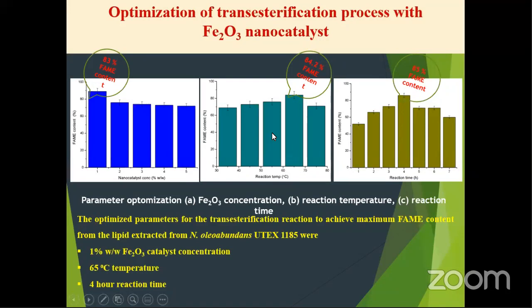and the reaction temperature varied from 35 to 75 degrees Celsius was considered for the study. And it was found out that for the case of 65 degree centigrade temperature, the biodiesel yield is maximum, that is 84.2% weight by weight. Maybe due to the high temperature, the viscosity of the biodiesel is less. So much more lipid comes into contact with the methanolic catalyst solution for the production of